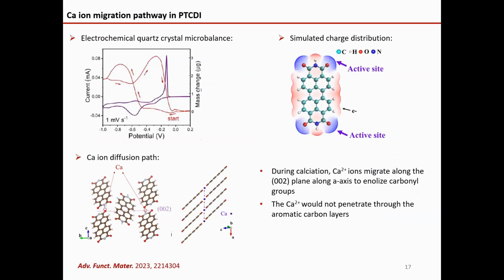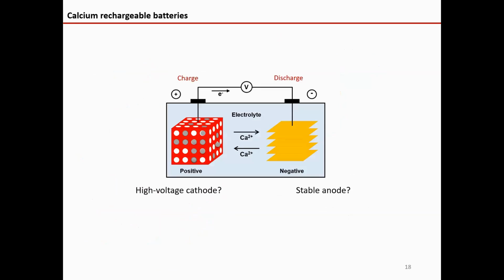I mean, the calcium ion will not go in here because this place is very small and it will be very slow for calcium to diffuse through. Through the EQCM and DFT calculations, we can determine that the calcium ion may go along the other directions. It's a fast diffusion path. So that is why we can obtain the fast charging anode materials.